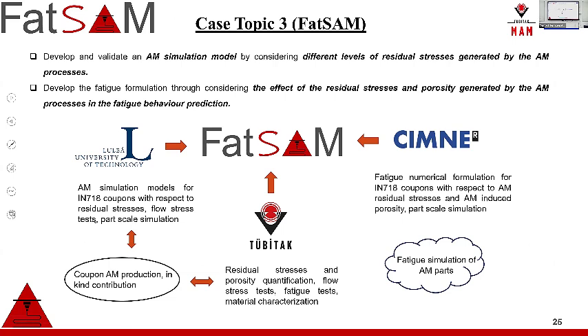I will keep it a little faster because it's a very long case study to present. What we are doing in FATSAM, just motivation. We have three partners, LTU, CIMNE, and us. We are applying mostly experimental work and provide data for CIMNE and LTU. LTU does the AM calibration, CIMNE does the upgraded fatigue model for these materials. I'm saying upgraded because most of the studies are currently high cycle. In this project, we will do low cycle fatigue, which is strain control, plus elevated temperatures, which is 3 different temperatures in addition to room temperature, which counts for 4, plus 3 different strain rates. So it multiplies for each temperature with 3 different strain ratios.